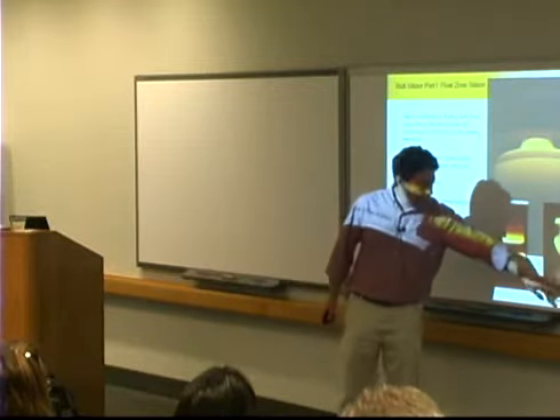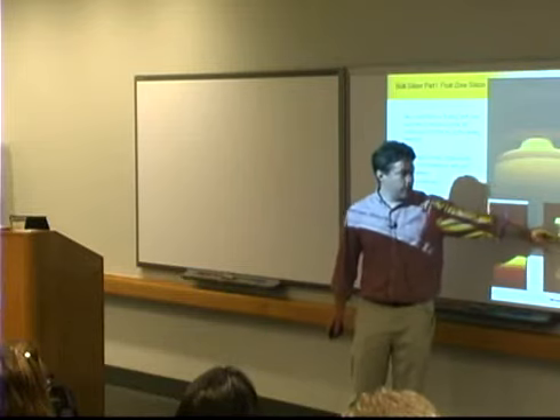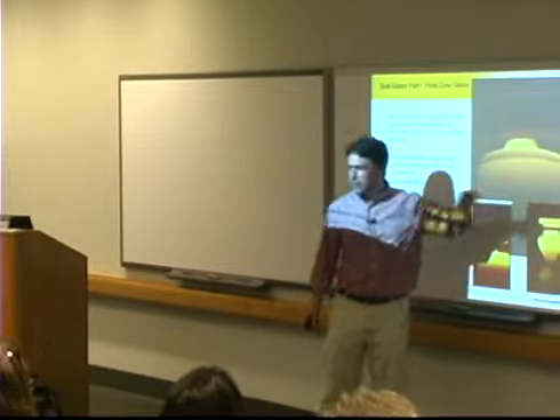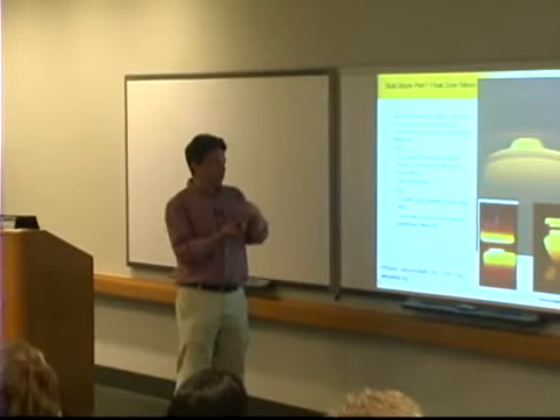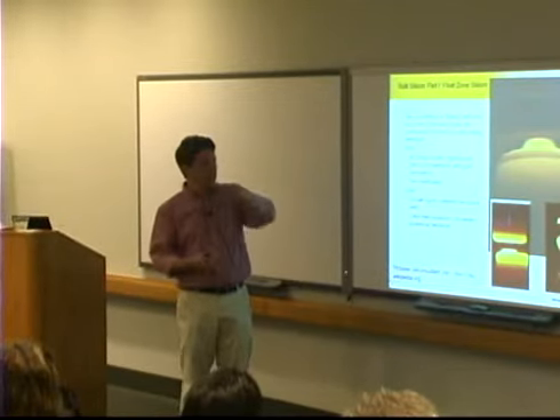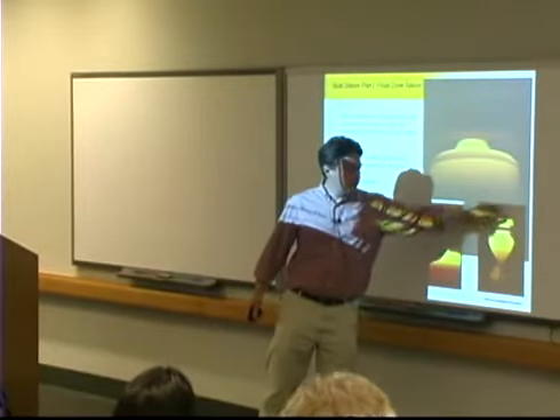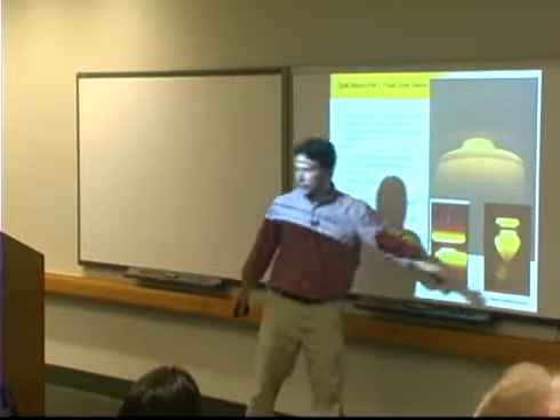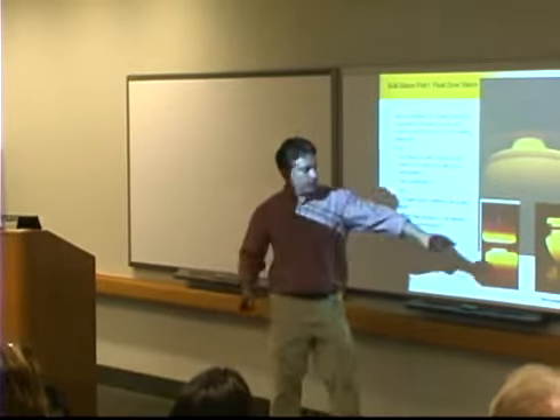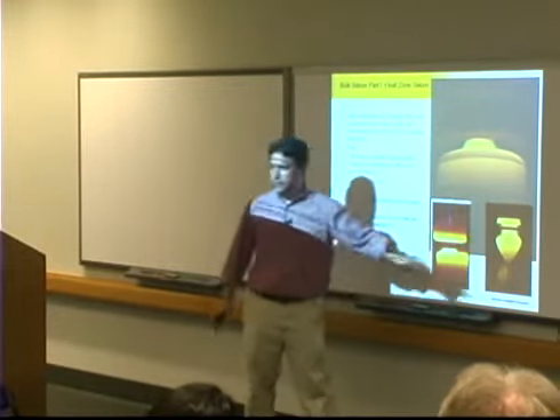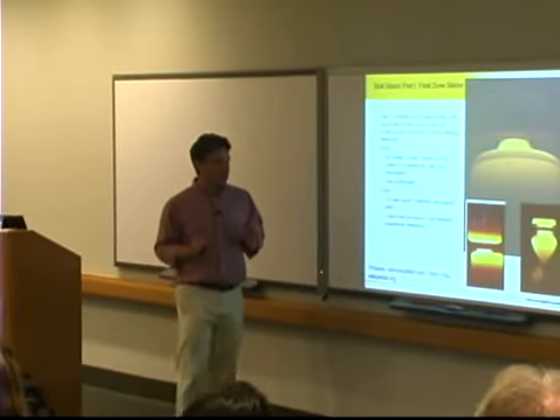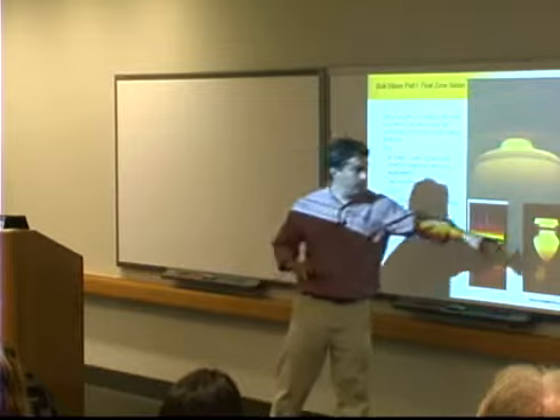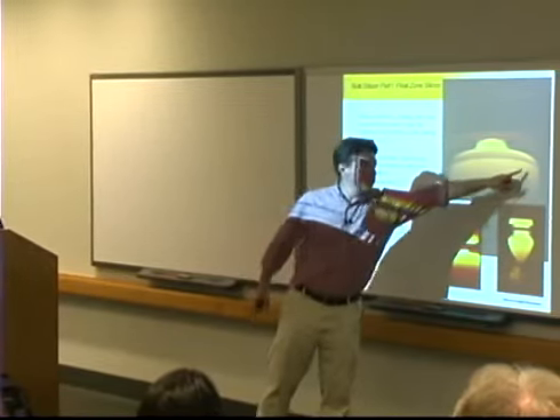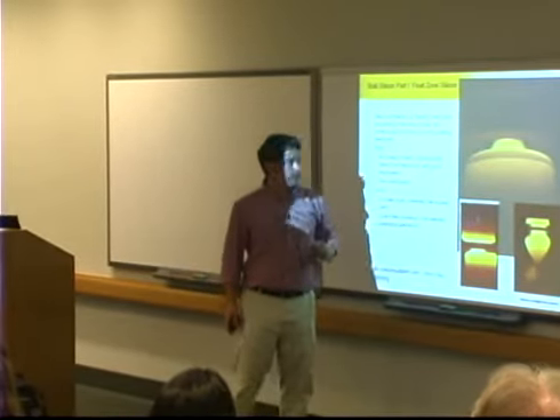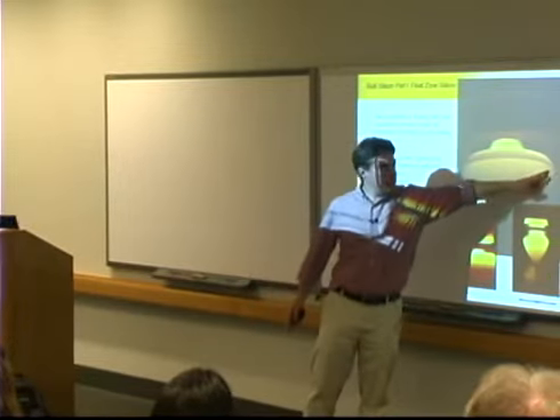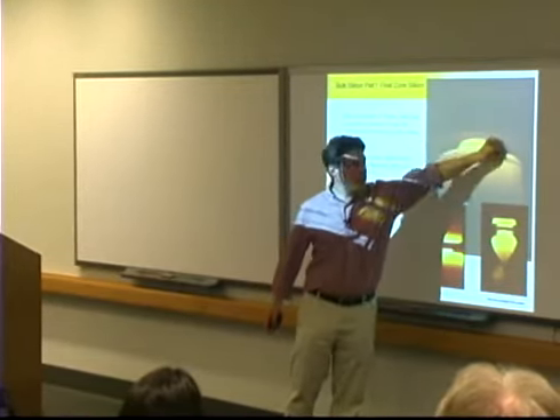And then what you do is you bring a seed crystal up from the bottom. This is a nice picture here. You bring a seed crystal up, and you touch the end of the melt, which is just kind of dripping off here, to the seed crystal, and then you start basically pulling down, and you keep the heat coming in from the coil here, and the amount of melting that you're doing, you keep that balanced with the rate that you're pulling down, and you can make this thing wider. You can see here that it started thin, and then they grew it wider in a typical necking process, and then once you reach your goal diameter, you can just keep this thing steady all the way. So you can see here is the edges of a float zone ingot that's in the middle of the growth. And here again is the high emissivity solid, and then the boundary to the low emissivity liquid that's sitting in a pool on top of it.